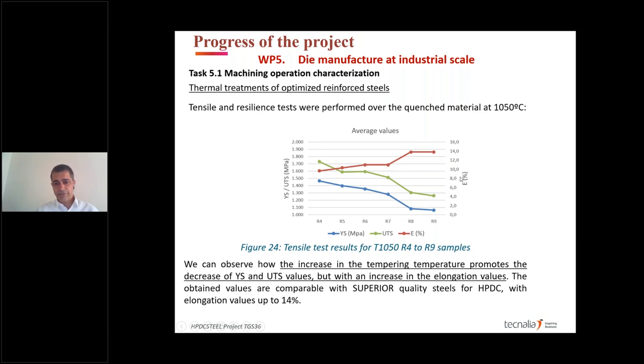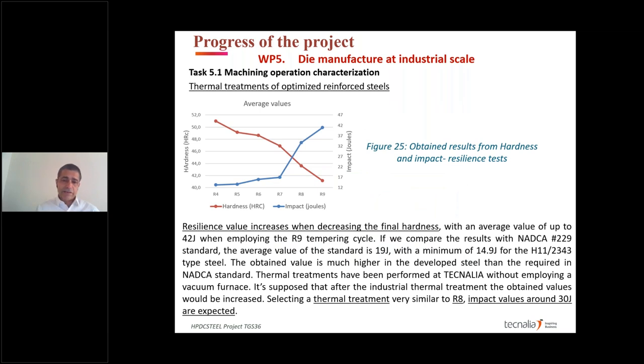So, for example, we can have 8% for the R7 tempering process. The same with the impact and resilience test. We wanted to know what happens with the resilience, and we made the same test, and we checked that we had quite good impact values in joules. These are the values, and what we see is that we have up to 42 joules, in this case 32, in this case 17.